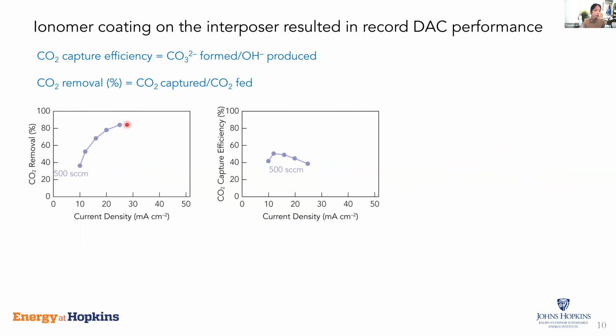Beyond this point, there's no reason that we keep increasing the current density because we're almost depleting the CO2 in the gas phase. In order to further improve the current density, we keep increasing the inlet gas flow rate to 1000 ccm, and then you can see we can push the current to about 50 milliamp per square centimeter with decent capture efficiency. And then how do we further improve the performance?